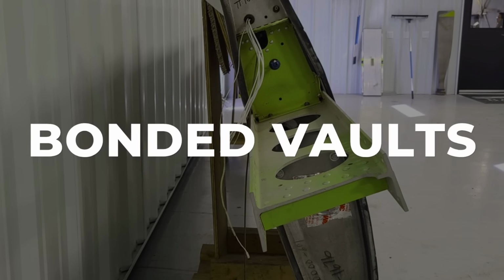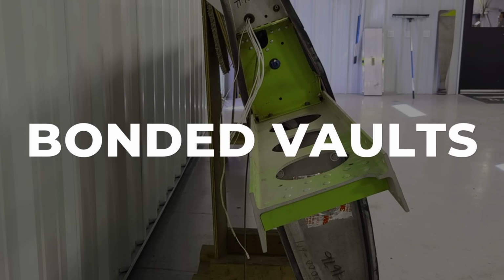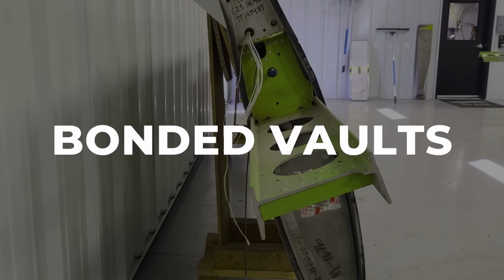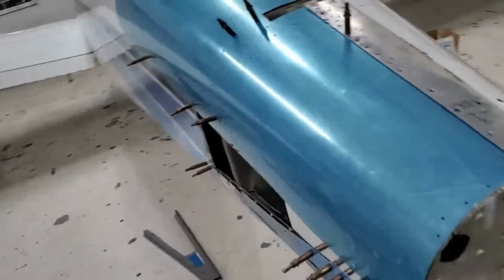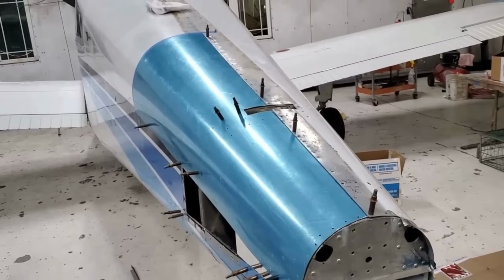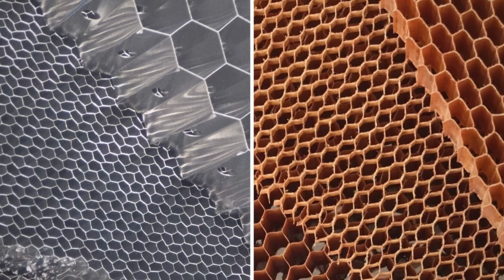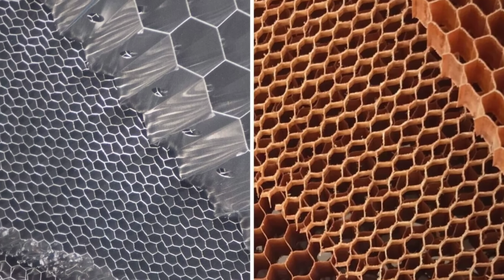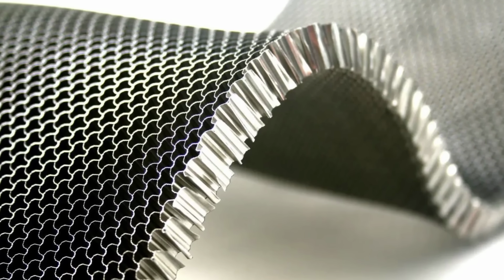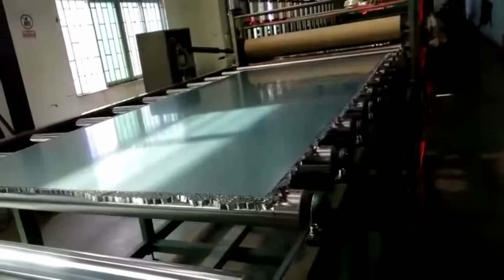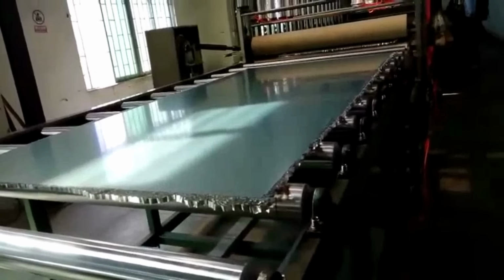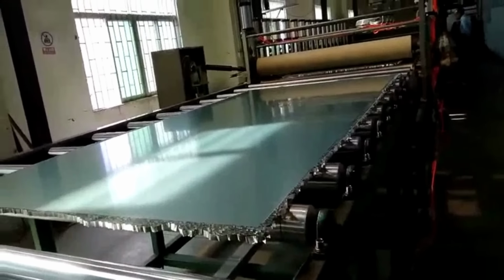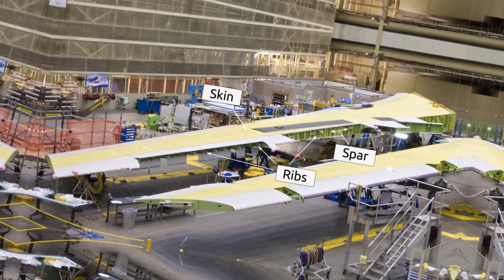Inside the Beechcraft Musketeer's wing, strength comes from a structure that looks more like architecture than aviation. Instead of ordinary ribs and spars, Beech built a sandwich of thin sheets of aluminum bonded to a honeycomb core. Each cell of that honeycomb is a tiny hexagon pressed from aluminum foil, stacked edge to edge, and glued between the skins. The result is a panel that resists bending and twisting far more than its weight would suggest.